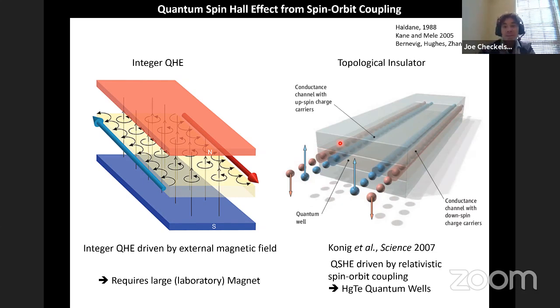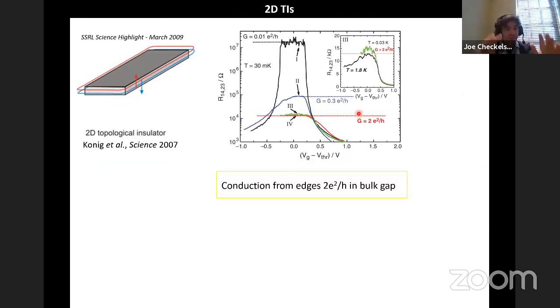But the fact that these systems are supposed to be non-magnetic, they have time reversal symmetry, means that if you have that kind of behavior for one spin of the electron, you have the same kind of behavior for the opposite spin, but in a counter-propagating fashion, such that these topological insulators get these boundary modes, but they're helical rather than chiral. And actually this notion that you have time reversal symmetry, or that they're not magnetic, is really what is important for their topological protection. So this was a theoretical concept that was borne out by experiment very, very soon after it was predicted. So this is how it was done in 2D.